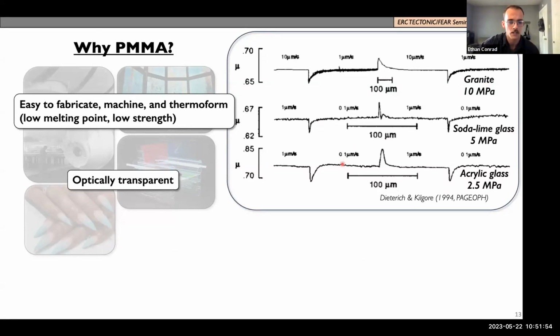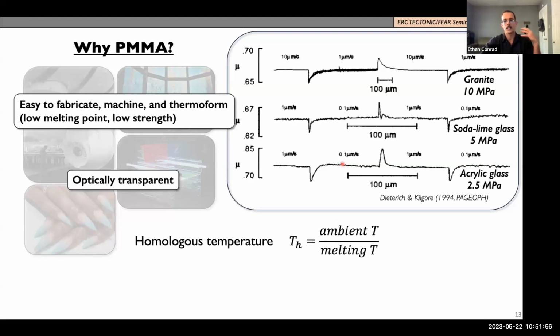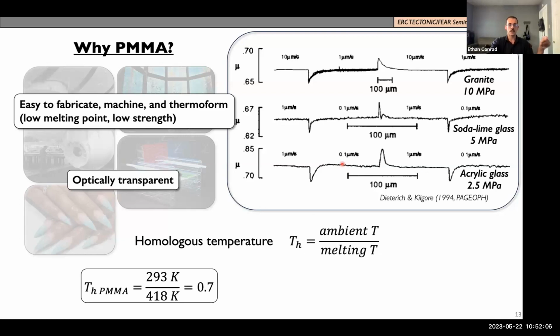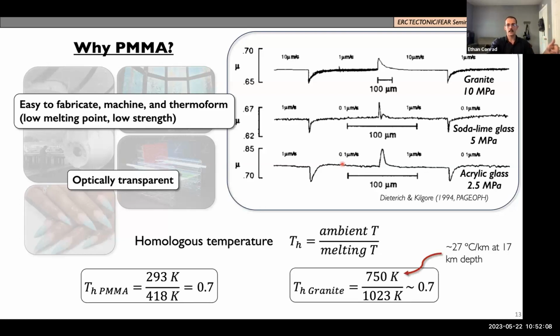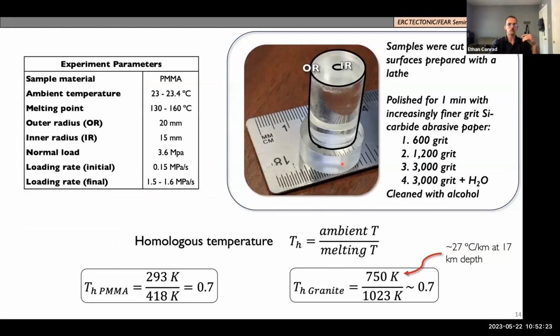And in a thermal framework, we can relate PMMA to granite through something called the homologous temperature, which is simply the ambient temperature over the melting temperature. That of PMMA is 0.7. It's also 0.7 in granite. So this is assuming a specific thermal gradient and some melting point. But nonetheless, it's in the same ballpark as PMMA, kind of testifying to the similarity in its properties.